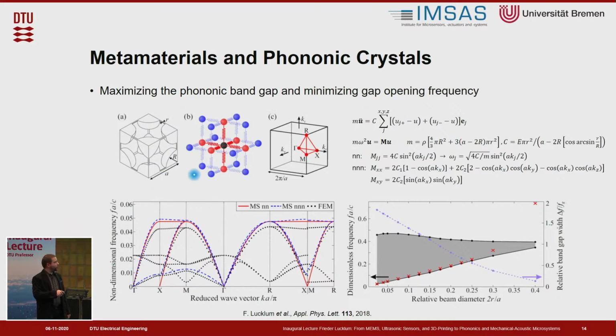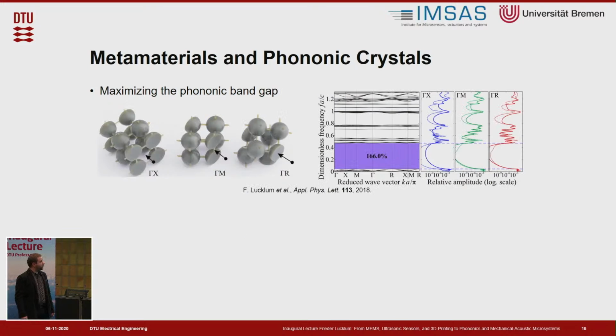And by tuning the geometric properties and optimizing the whole mass and spring arrangement, we can optimize and maximize this band gap, the width of the band gap, and also the position of the lower frequency. And this is exactly what we have done. These are some 3D printed samples, photography samples, so they were not used for measurement, just for illustrating the 3-dimensional structure. So you see it's a mass or ball and beam structure with big masses and thin beams. And this arrangement indeed shows a very wide band gap, which was at the time the largest and widest band gap reported in literature until very recently.